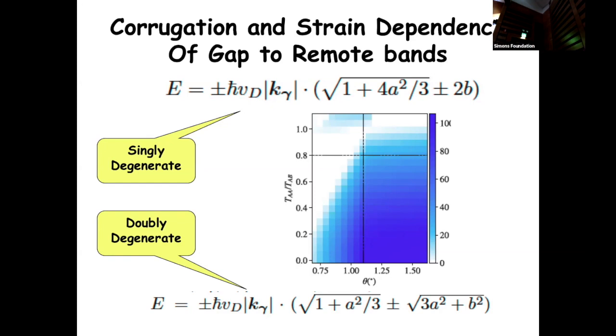let's just mention the simplest idea, which is corrugation. So it turns out these graphene sheets are most stable with a certain type of stacking, AB stacking. So the layers end up being closer together when they locally have AB stacking, and that makes the tunneling between the layers stronger in the AB regions of the crystal.